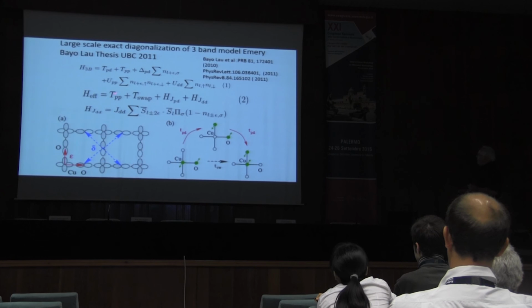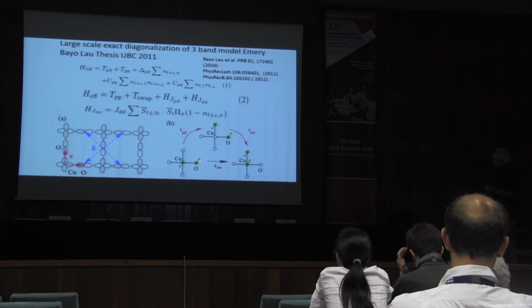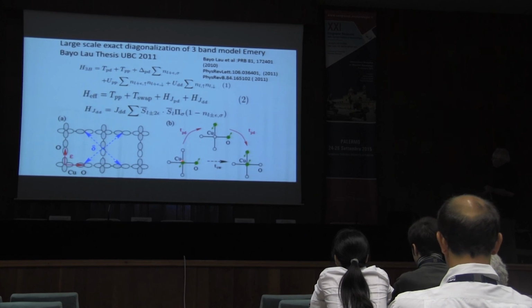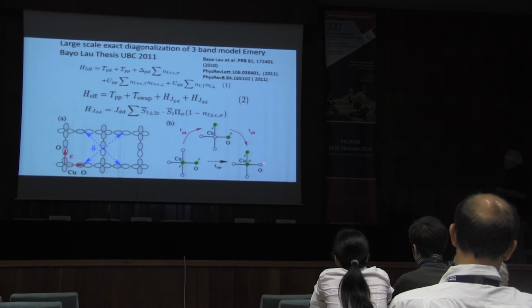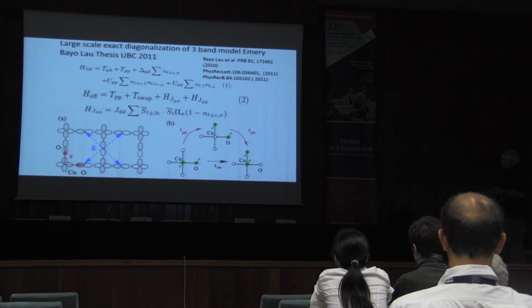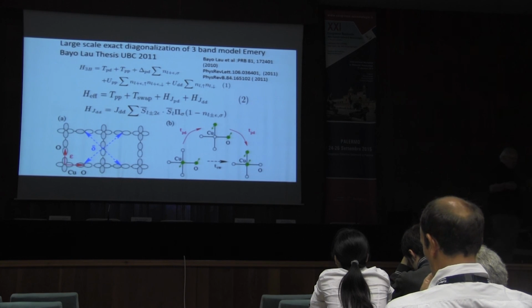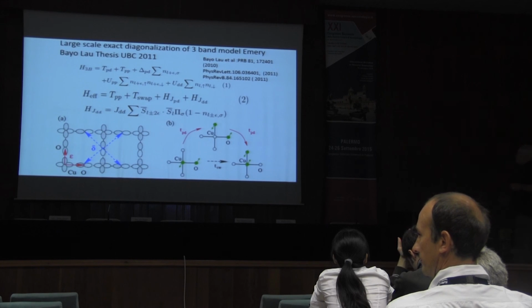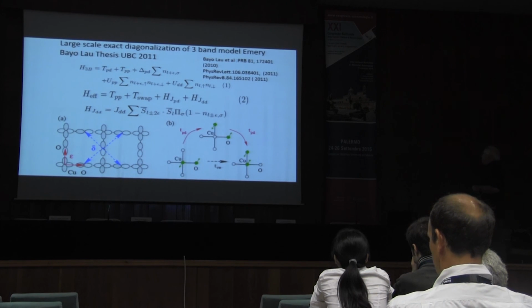Hopping integral between the oxygen orbitals here, and it gives you a hopping integral between the oxygen and the copper. And there's one very special term that's very interesting. If I have a hole on the oxygen and a hole on the copper, then the copper hole can hop onto that oxygen, giving you this. And then this oxygen can move on to the copper, giving you this. And now effectively, compared to this, you've hopped this hole into that oxygen, but you flipped its spin and you flipped the copper spin. This is almost a Kondo-like term, but it's a very interesting term and the most important term, actually, in the Hamiltonian.